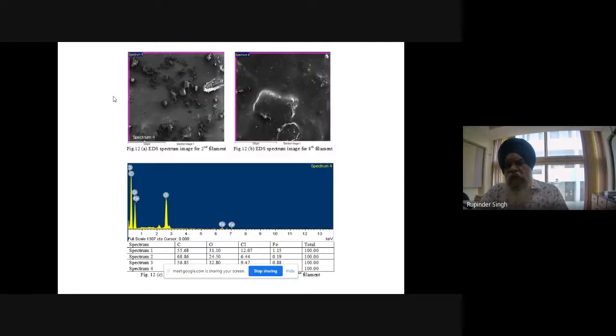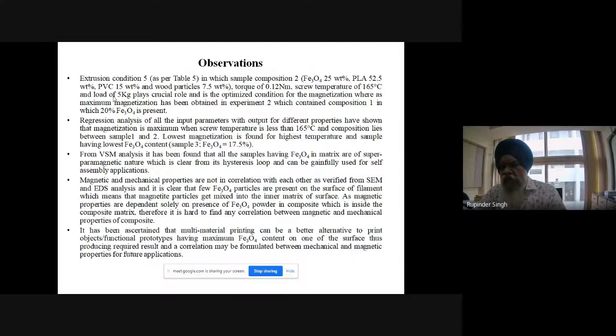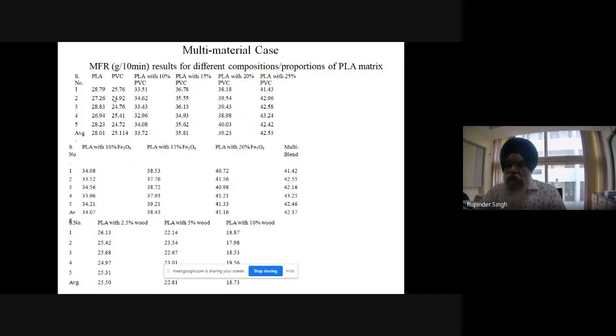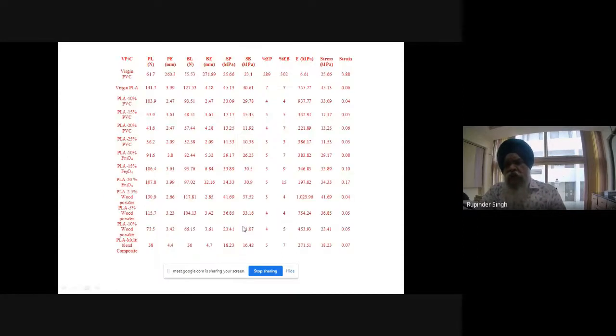Did some parametric optimization, did some SEM analysis, some EDS analysis, and we tried to see their effect on their melt flow index by putting different proportions by weight, 10, 15, 20, 25%, and similarly with different variation of Fe3O4, different variation of the wood powder into it, and we tried to see the effect on their mechanical properties. Like for the virgin material, what was there, then with the level of reinforcement, what is the change in their peak load, peak elongation, break elongation, peak strength, break strength, Young modulus, then their stress strain value.